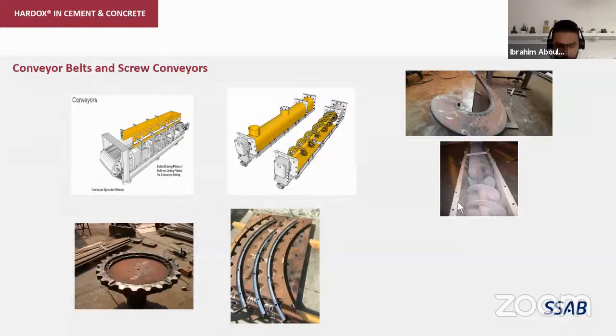On the bottom of the slide, there is 2 pictures for clinker conveyor sprockets, and we have a lot of customer cases that proved the great service life increase and the performance increase when it comes to Hardox 500 with thicknesses especially higher than 55 millimeter. We solved a lot of problems with a lot of customers in that. Next slide, please.